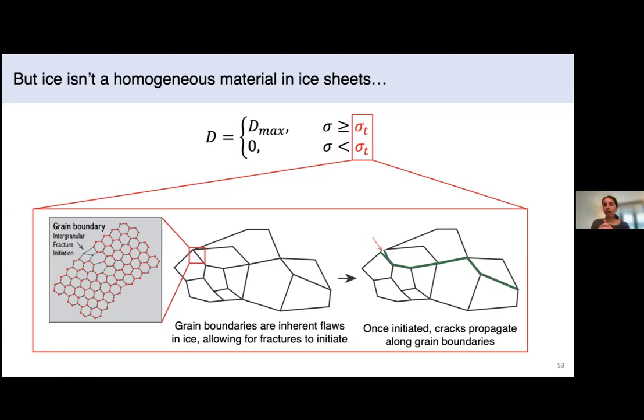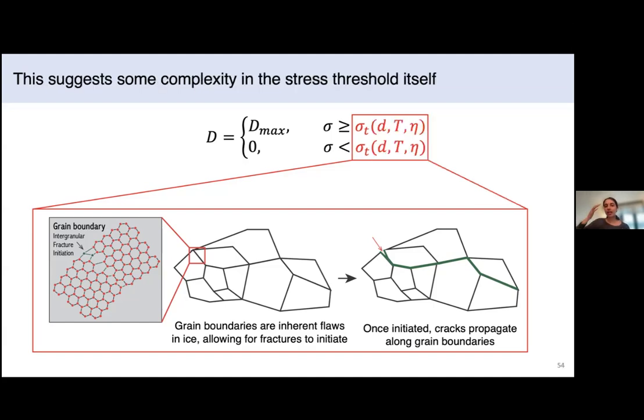So this is just a thought exercise to suggest that there are some controls on ice strength that come from the underlying microstructure of the ice, the material properties of the ice, how warm the ice is. All of these things suggest that rather than treating ice strength as a single value, it might actually be a more complex phenomenon that is responding to changes in microstructure, temperature, and even the viscosity of ice itself might contribute to altering strength. What this means is that we might expect ice strength to change spatially and temporally. So ice strength should be different in a shear margin versus in the trunk of an ice stream.